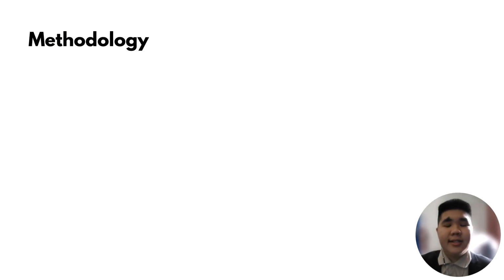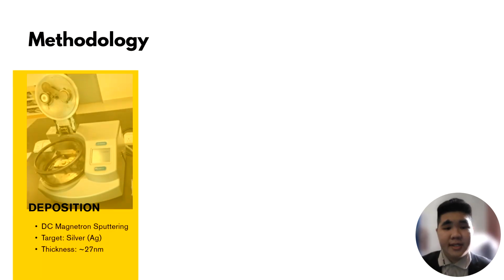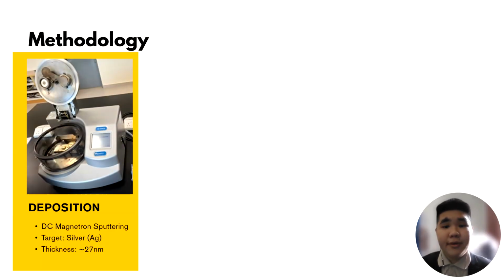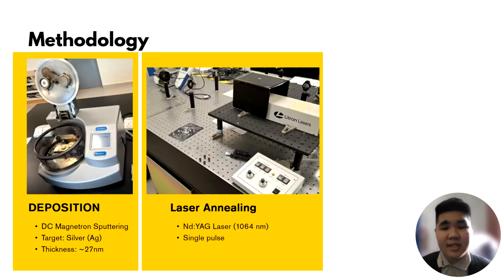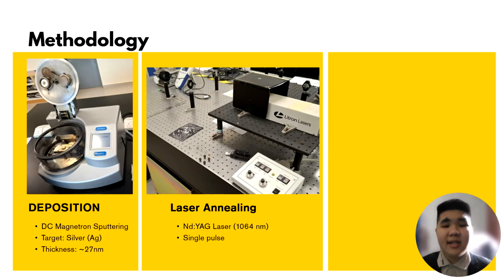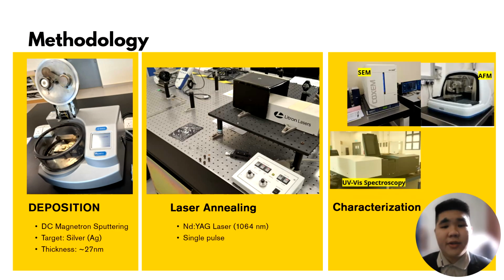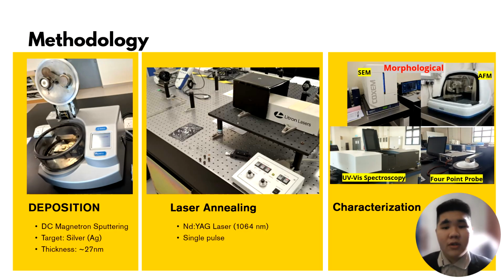Our methodology consists of three phases, where first is the deposition phase. We use the DC magnetron sputtering method to deposit a precise 27 nanometer layer of silver onto the PET substrate. Moving on is the laser annealing phase, where instead of using a slow oven, we use a 1064 nanometer Nd:YAG laser. By delivering rapid nanosecond pulses to the surface, we heat the surface instantly. And finally is the characterization, where we verify the result using SEM, AFM, UV-Vis spectroscopy, and 4-point probe for morphological, optical, and electrical analysis respectively.